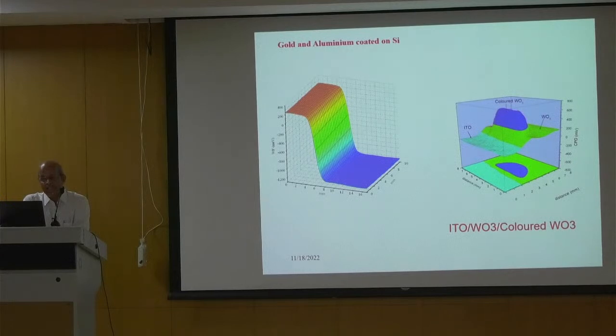tungsten oxide lattice. If you are pushing positive ions, what is going to happen to the Fermi level? The Fermi level has to come down towards the valence band. So there is a change. That change has been brought about here because we need an electrode which is transparent and conducting. We have taken tin doped indium oxide, ITO, and then we coated the tungsten oxide on ITO, and on a part of the tungsten oxide we put a drop of hydrochloric acid. Then we put a circuit, with an electrode at the bottom with ITO through a battery. We push this hydrogen ion into the tungsten lattice through an electric field. Then this tungsten oxide becomes bluish in color.